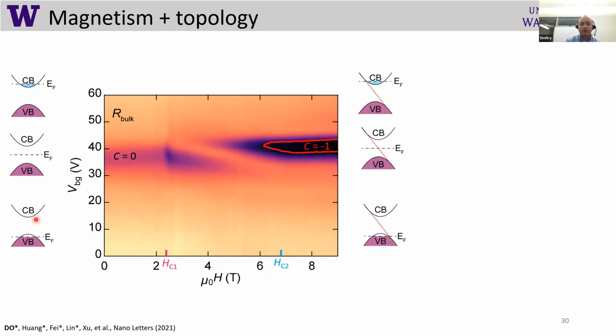And on the right side, we know that there is an edge state. I already showed them to you. And again, by changing gate voltage, by changing the vertical axis, we change the position of the Fermi level. So for example, here we are in the middle of the gap and the Chern number is 1, and we can measure the Hall effect here. As I said, the horizontal axis defines our external magnetic field, defines our magnetic states, and we can watch what's happening here.